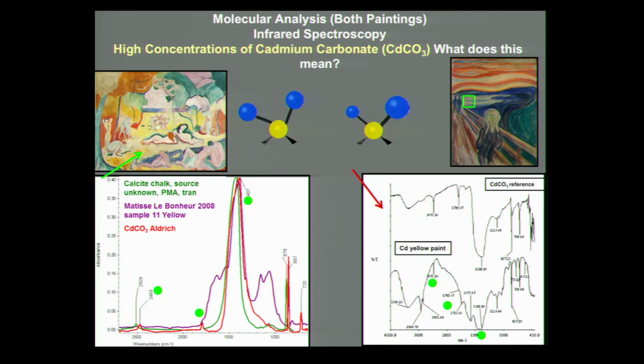And so before we did that, we went on and did molecular analysis of the paintings using a technique called infrared spectroscopy. This is a molecular fingerprinting technique where we're using the patterns of molecular vibrations in order to identify the different compounds that are present. And it turns out that in both the Joy of Life and the Scream, we see high concentrations of cadmium carbonate, and the green spots here are pointing out the peaks for cadmium carbonate.